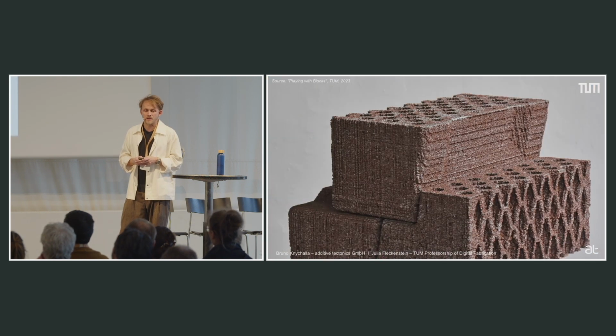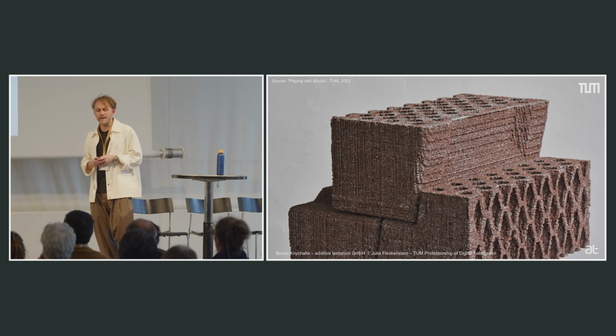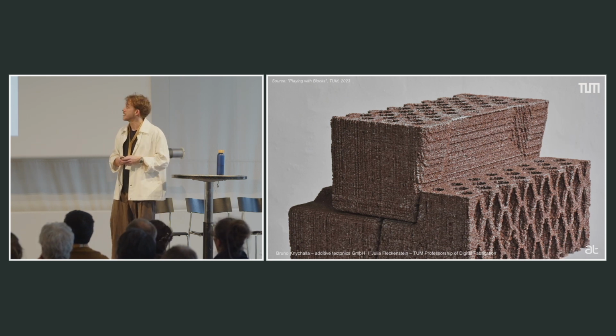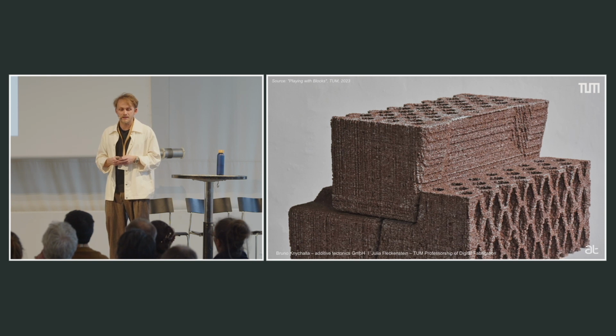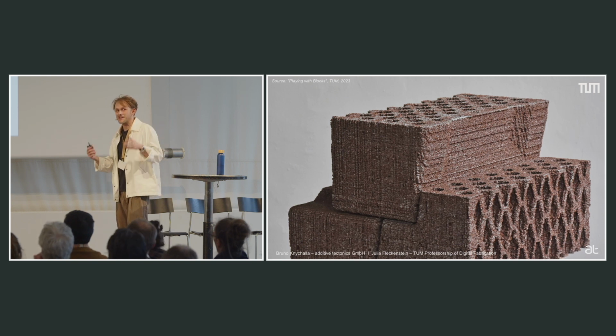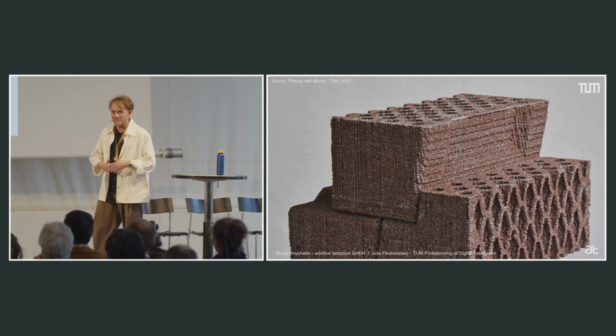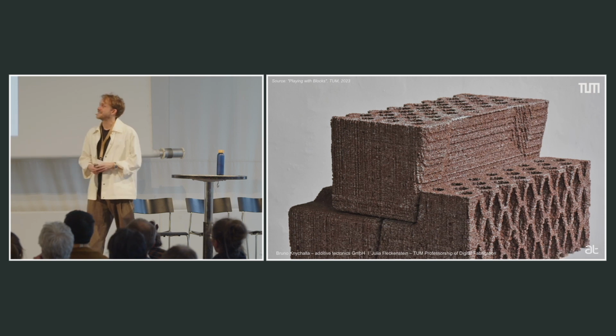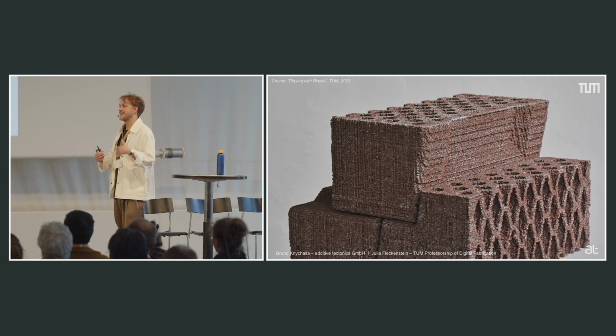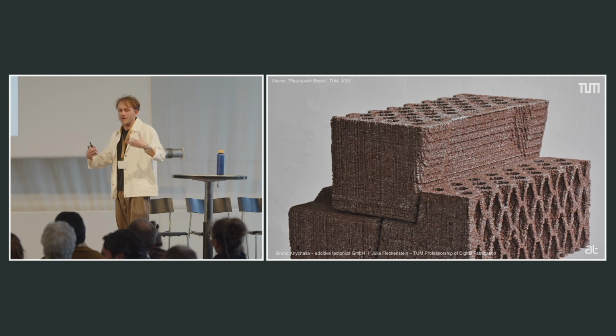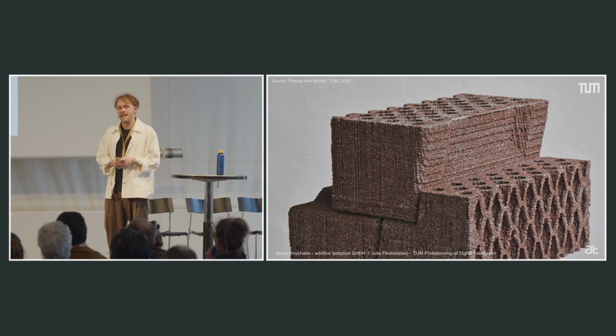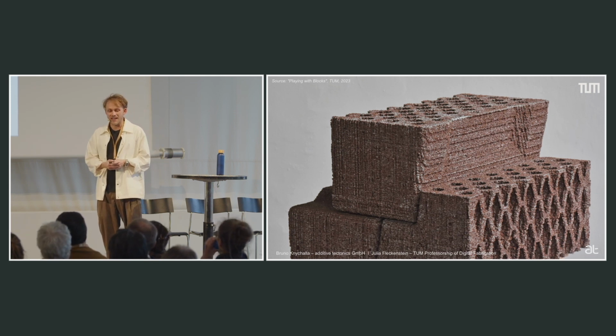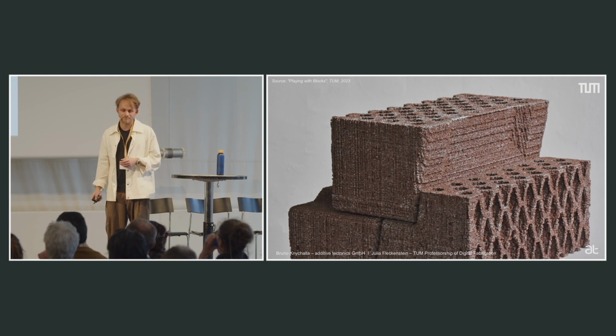A future way to solve this issue would be to trap loose particles inside the element during the printing process. In 3D printing terminology, this is called powder trapping or particle trapping. And this process is basically like a blow-in insulation, and we can achieve this by slightly changing our fabrication parameters.